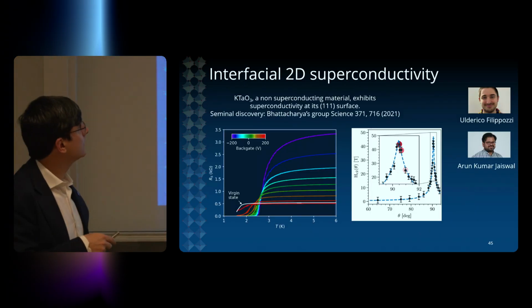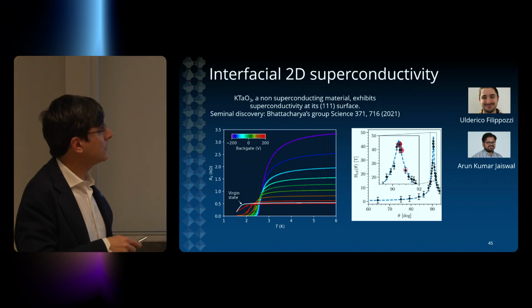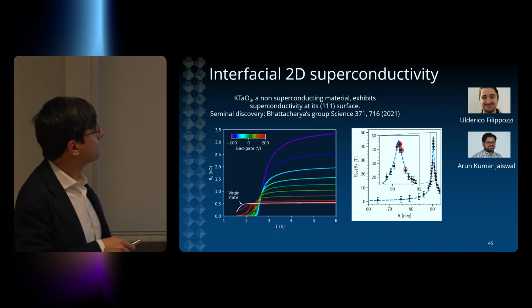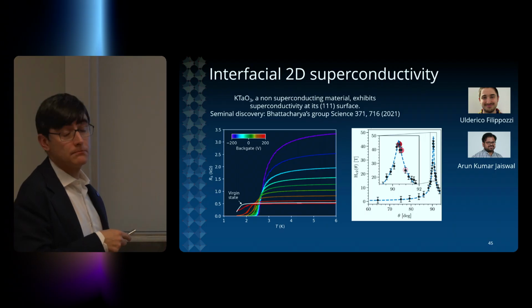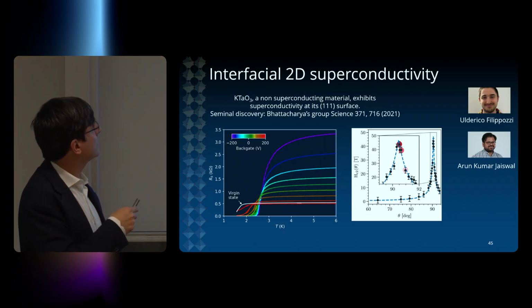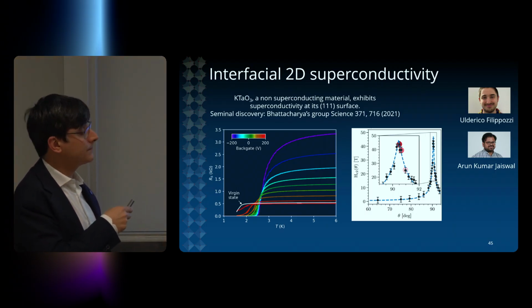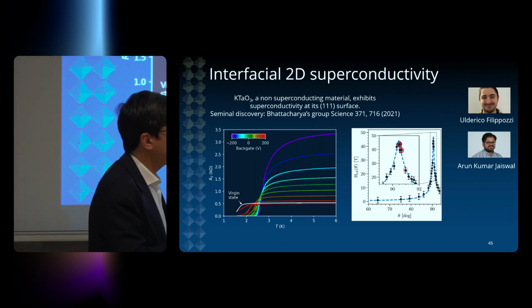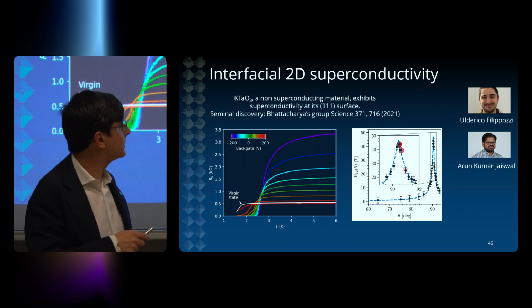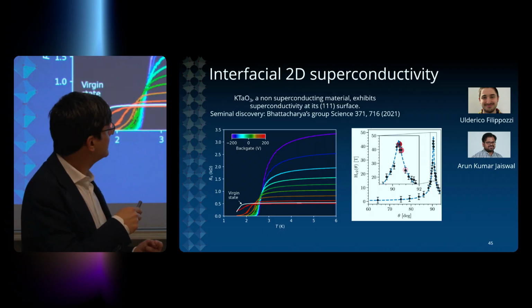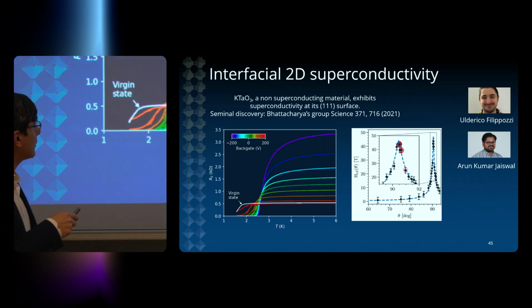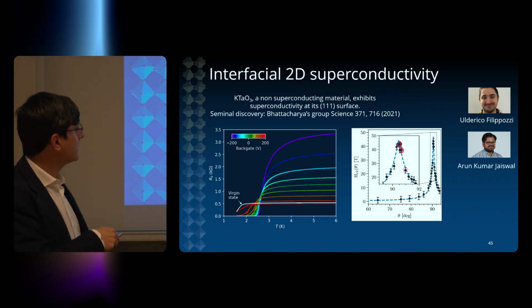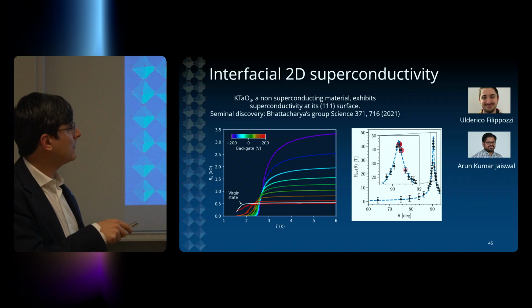And now one of the latest results from our group here. There is a new superconducting interface based on another interesting material called potassium tantalate. This material is never superconducting in the bulk, even when doped. But at its 111 surface, it shows a very robust superconducting state with a critical temperature that can be as high as 2.6 Kelvin. This is a discovery made by Ulderico and Arun here. Here I'm showing data that is still unpublished.